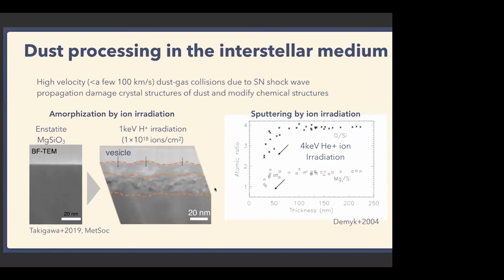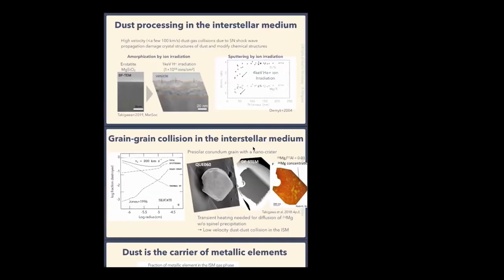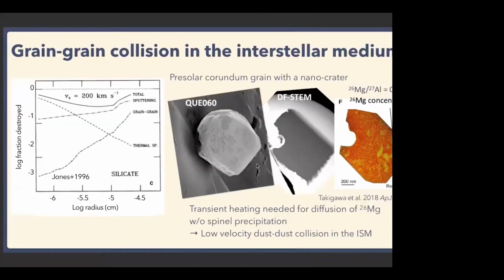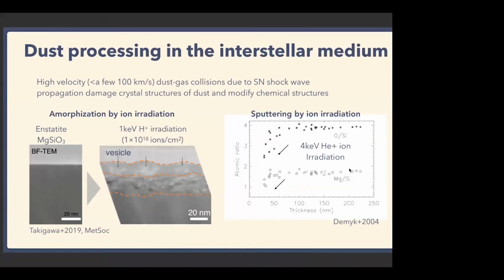Also, the chemical composition is changed due to the irradiation from gas-dust collisions. This shows the oxygen to silicon and magnesium to silicon ratios changing due to the irradiation. The magnesium to silicon ratio decreases as the dust is irradiated. So not only the structure but also the chemical composition changes through gas-dust collision in the interstellar medium.